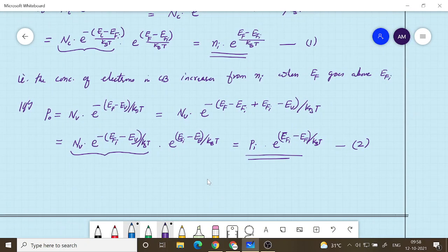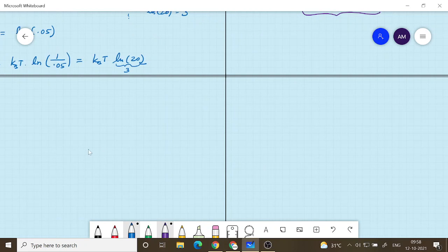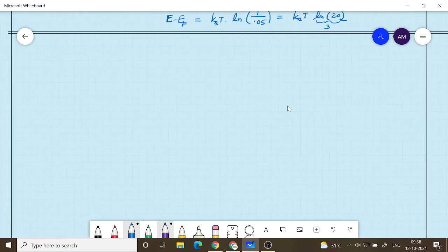So this equation says that the number of holes in the valence band is going to increase above Pi if this quantity is larger than 1. That is when EFI is above EF, or in other words, when EF, that is the Fermi level, goes down, then exponentially the concentration of holes increases.